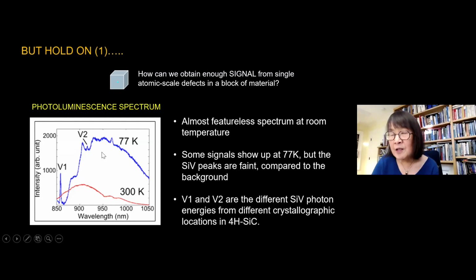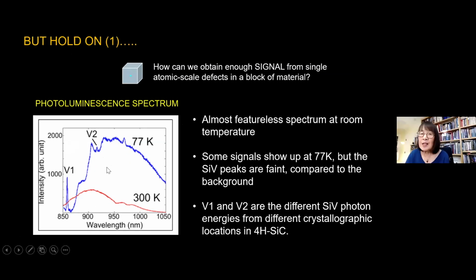I showed you two vacancies in earlier schematics. There are slight differences in the crystallographic environment that lead to this distinguishing difference in the photon emission signature of the silicon vacancy. So this is both good and bad. It's very impressive that a missing silicon has such sensitivity to its home location in the starting crystal that it gives you a distinctive photon signature. But the what if remains. And the what if is, how are we ever going to pull a reasonable signal out of the noise of these spectra?